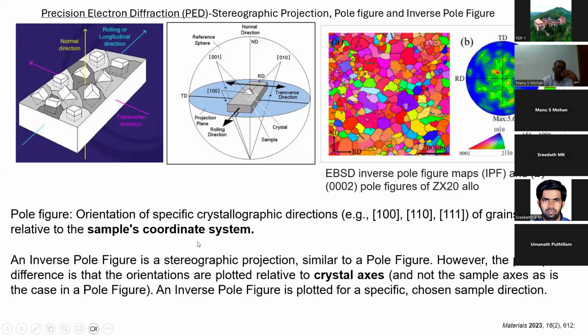inverse pole figure and the pole figure. Pole figure is nothing but when the orientation is plotted relative to the sample's coordinate system. You have the transverse direction here, RD, and if someone asks to plot 100, it can be plotted, because all it is doing is taking the grain, keeping it at the center of the sphere, with RD-TD as the sample coordinate system axis, and then keeping the unit cell at the center and plotting its 100 pole on the 2D plane, according to the procedure I told earlier. So you get a distribution.